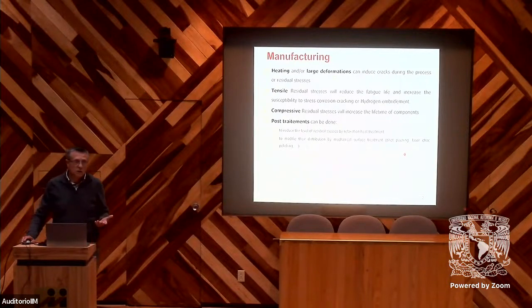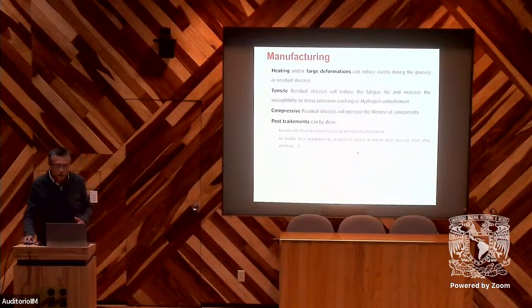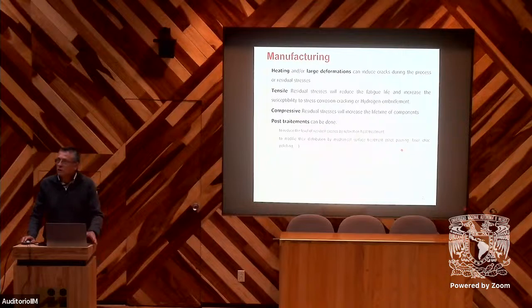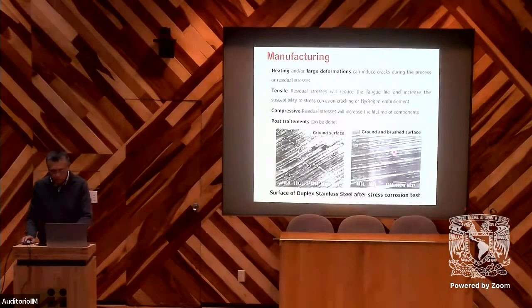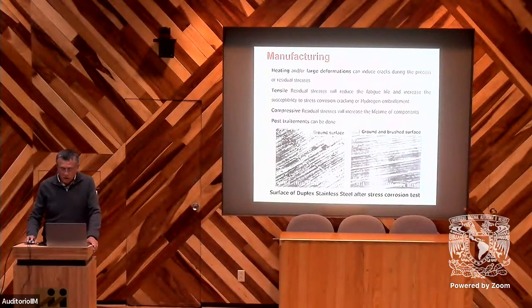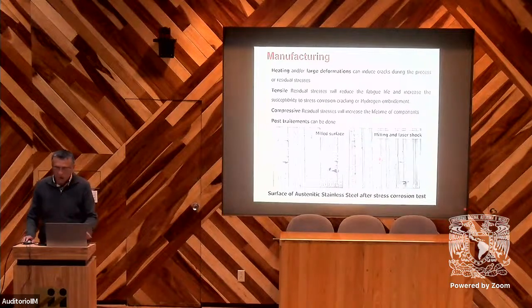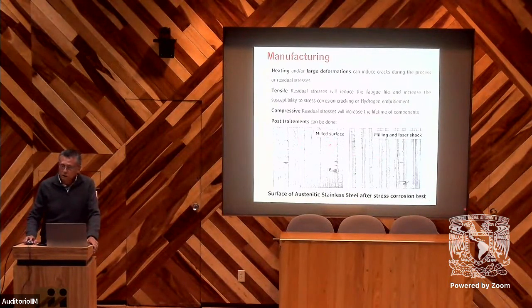So to reduce residual stresses, we can use some post-treatment, for example, heat treatment to release residual stresses, or we can also introduce compression by post-treatment, for example, by shot peening, laser shot peening, or polishing, and so on. We can see in this example that with grinding, we can have cracking after corrosion tests. And if after grinding we make a brushing, we induce compression, and so there are no cracks after the corrosion test. Same results if we compare the surface after milling and the surface after milling and laser shock: in the first case there are cracks, and in the second case no cracks after the corrosion test.